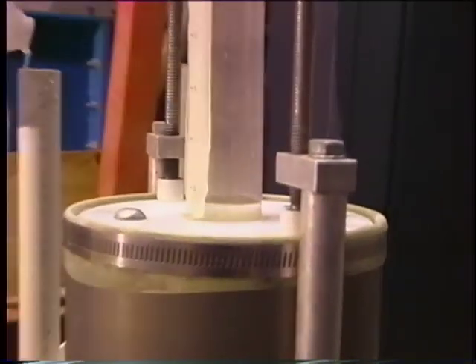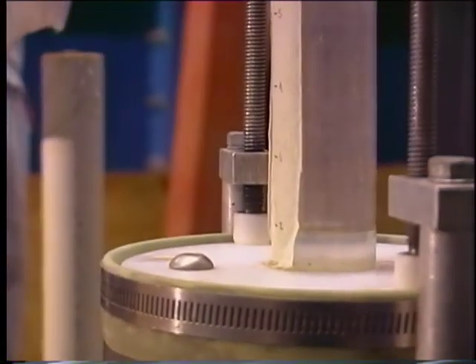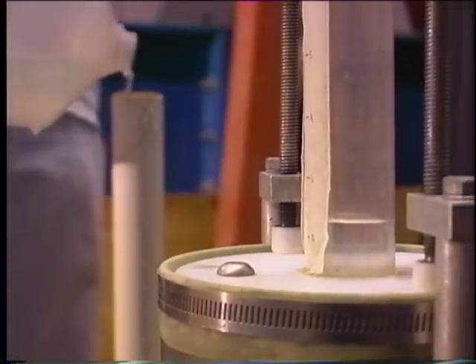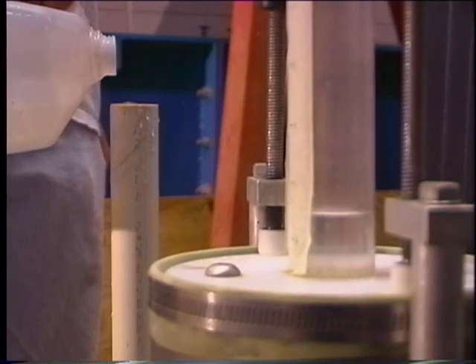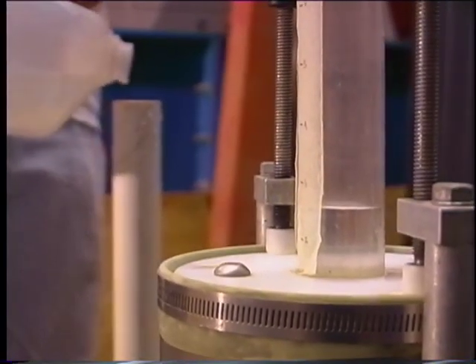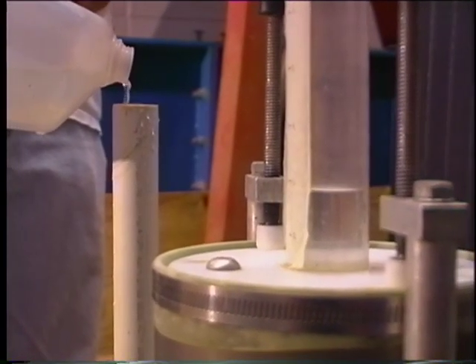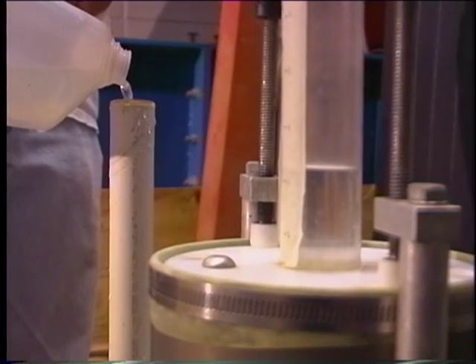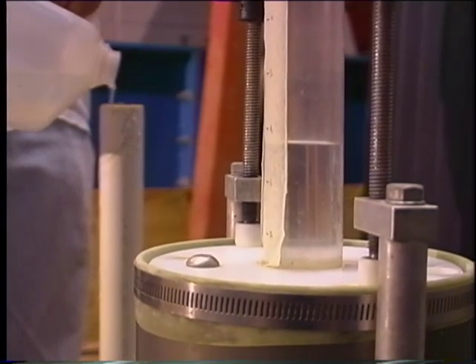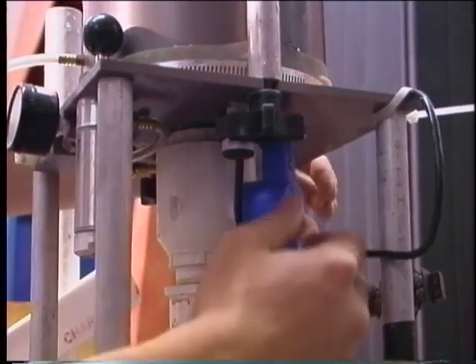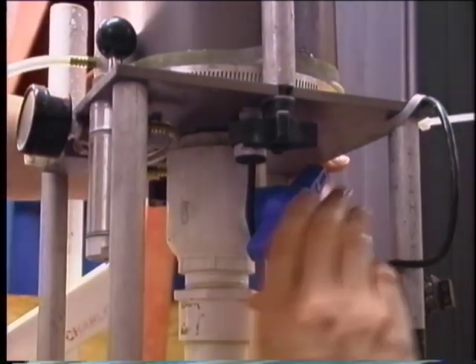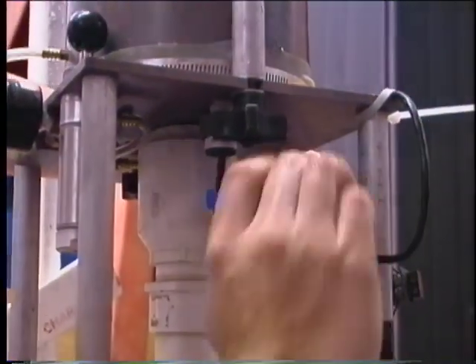Water will enter the chamber and tube and come to equilibrium with the PVC pipe around the 5-inch mark of the tube. The system must be at equilibrium in order to add pressure to the chamber. Close the upstream or blue valve under the stand when water reaches equilibrium. This valve will be opened later to start the test.